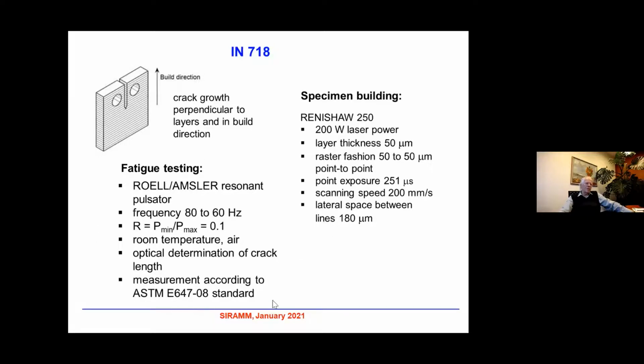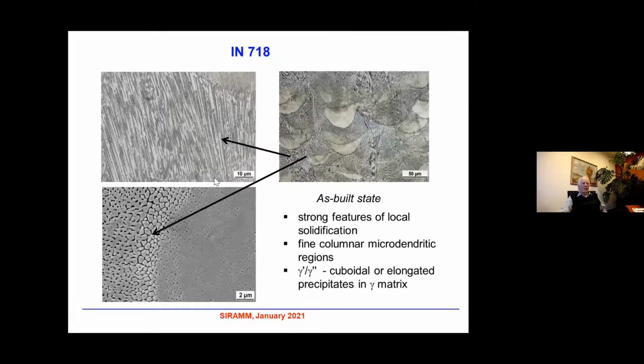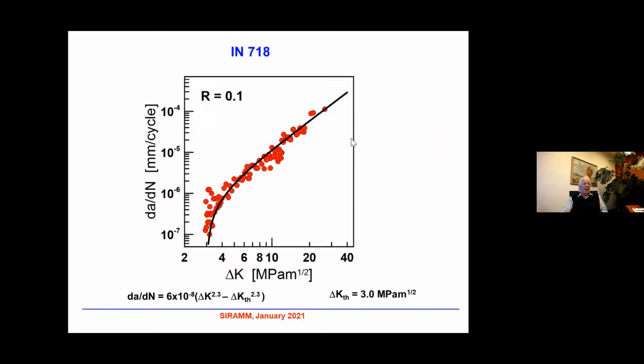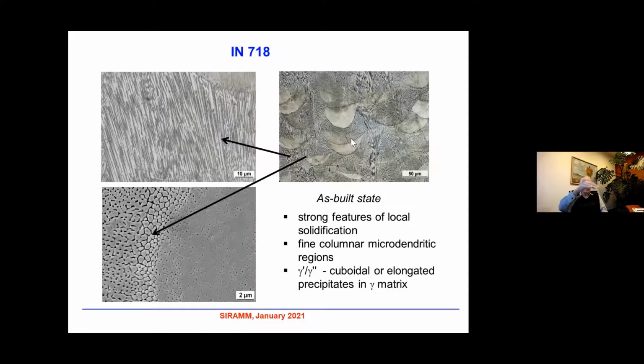And the fatigue testing was performed again on our Roell/Amsler resonant pulsator. Some words on microstructure. You can see that the microstructure of as-built material is really complicated. On the right-hand side, you can see strong features of local solidification. Here you can see these melting pools. You can see fine columnar microdendritic regions, for example, in this region. You can see gamma prime, gamma double prime, cuboidal or elongated precipitates in the gamma matrix. So the microstructure is extremely complicated. It is important to say that it is similar in all directions in this case.